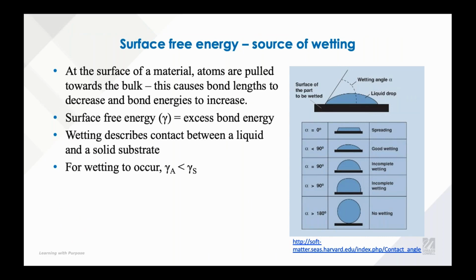So focusing a little bit on wettability, which has been brought up a little bit. When we're talking about wettability, the classical image of it is that we have a solid substrate, and then there's a liquid droplet that's put on that substrate. If we have good wetting in the system, then the droplet spreads. And if we have poor wetting, then the droplet will bead up. And this is important for a wide range of applications. You can think about coating processes where you want to make sure that you have good wettability. You can also think about superhydrophobic surfaces or self-cleaning surfaces where you want the droplets to bead up and then roll off and clean off dirt along the way.